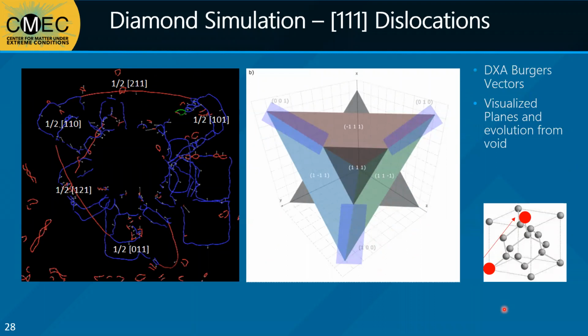When we perform DXA analysis on the simulation, we obtain these values for the Burgers vector of those dislocations. The rectangular blue dislocations match up with those previously found in the diamond nanopillar compression experiments of Nia et al., forming along the 100 family of planes in the 110 directions. In the nanopillar compression experiments, these were instead loops, but our loops are instead along the 111 family of planes with a 211 direction. The most typical type of dislocation in the 211 direction for cubic systems is the Shockley partial defect, one of which can be seen here in the simulation.